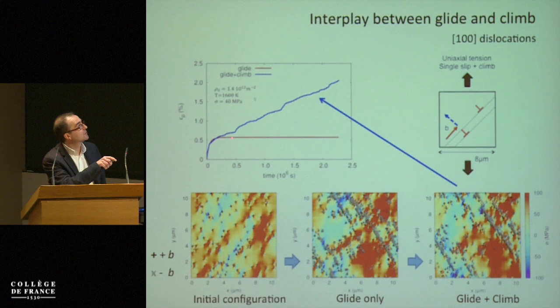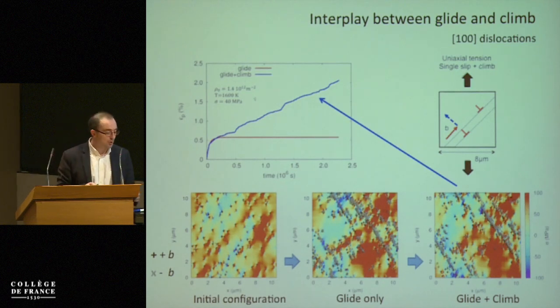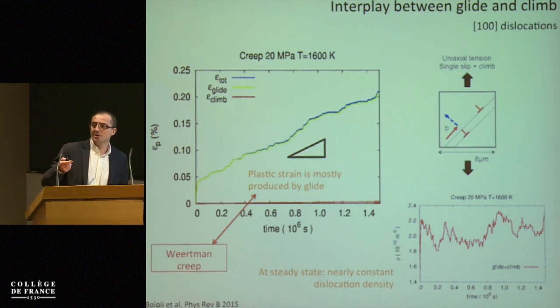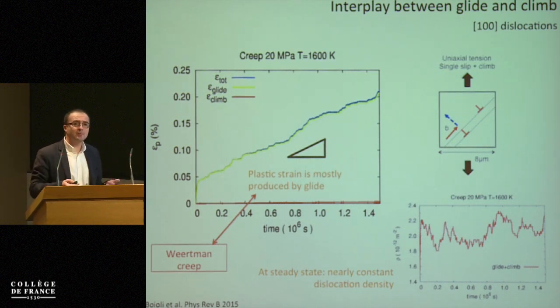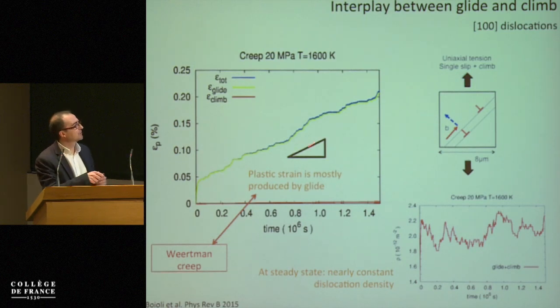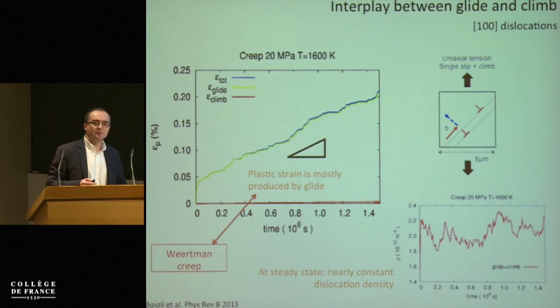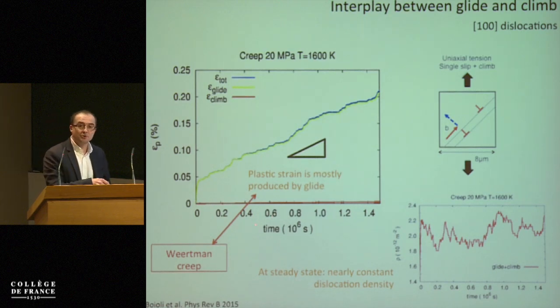From this plastic strain versus time curve, we can extract the strain rate for a given applied stress condition. Importantly, when we compare the amount of strain produced by glide versus by climb, we see that climb does not itself produce any strain — all the strain comes from glide. However, climb is very important as the mechanism that allows dislocations to continue moving and deforming the sample. This kind of dislocation creep mechanism is well known and is called the Weertman creep process.